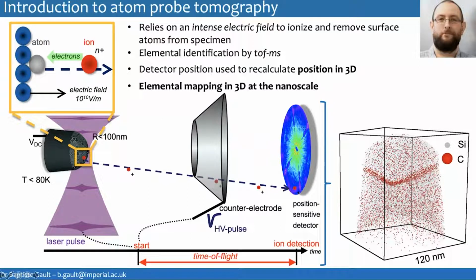So we know when we pulse the laser or the voltage, so we get an idea of the time of flight. And from the time of flight, we can figure out the mass of the ion. And from the location on the detector, we can figure out where it was in the tip to begin with. So what you end up with here is a 3D reconstruction, like the one in the corner. This is a silicon sample with a grain boundary and carbon on the grain boundary. And you end up with this 3D reconstruction of the location of individual atoms within the sample.